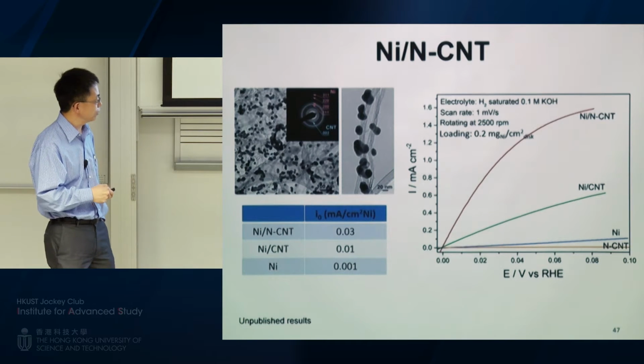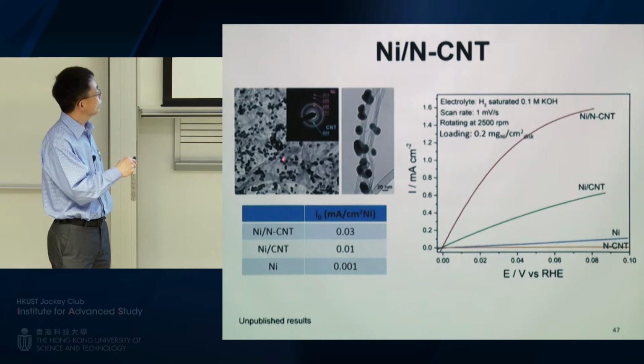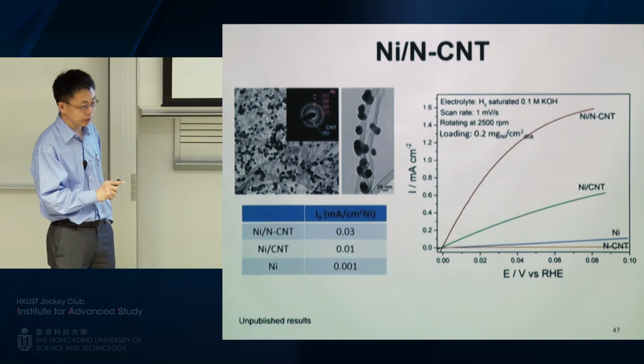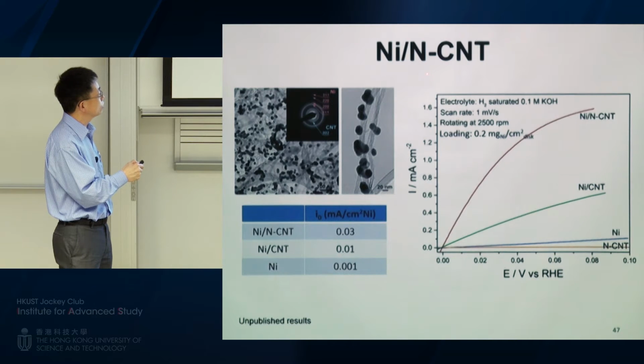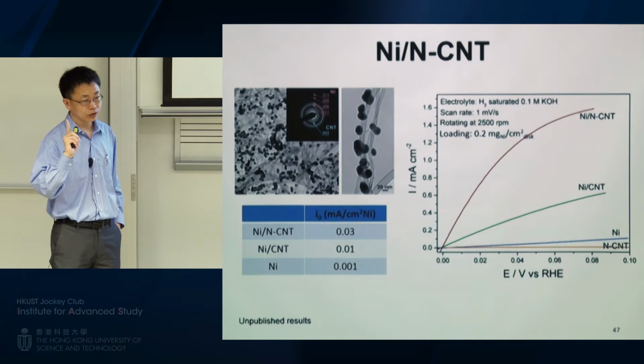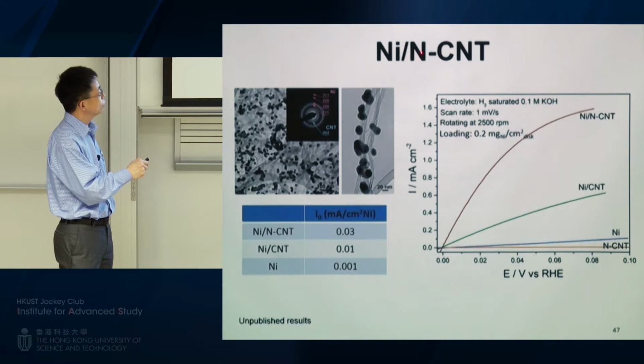At some point in time, I need to submit a paper. So this is a nickel supported on nitrogen-doped carbon nanotube, and this is the TEM picture. The reason we tried this, we also have calculation, which I'm skipping today, and the other is the intuition. When you have nitrogen-doped carbon nanotube, you have one extra electron on the nitrogen, which is possibly donated into the nickel atom so that you can reduce the binding energy.